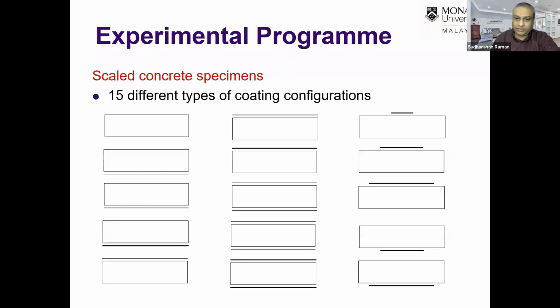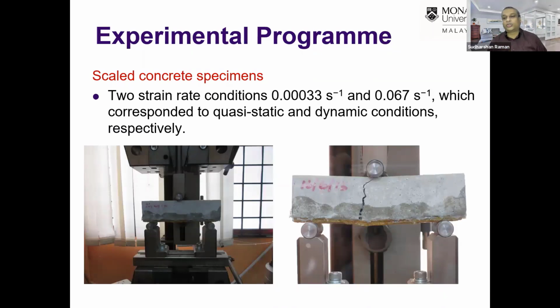We also tested them under two strain rate conditions, 0.00033 as well as 0.067, just to look at the variation of strain rates and how it influences the behavior of the coating as well as the bond characteristic between the coatings. In this study, we also studied the bond behavior between polyurethane and concrete under varying slipping rates or varying strain rates, but I would not be presenting those results here. This is one of the works which will be published in the near future.